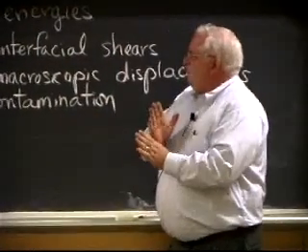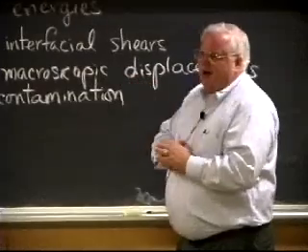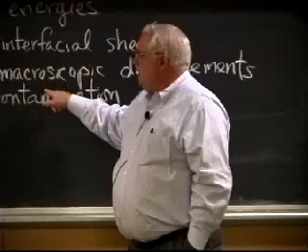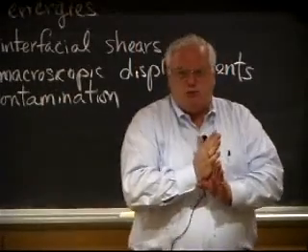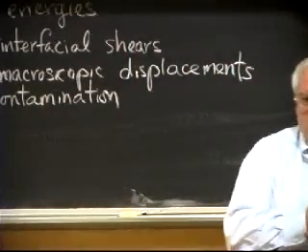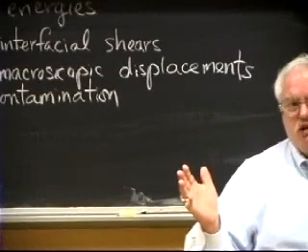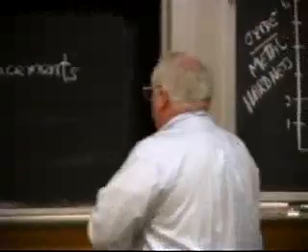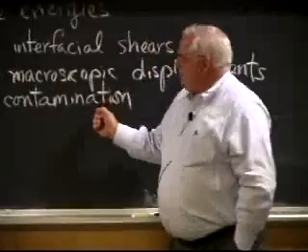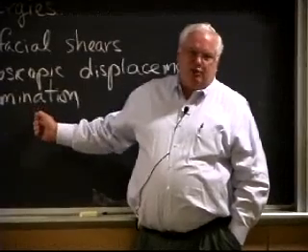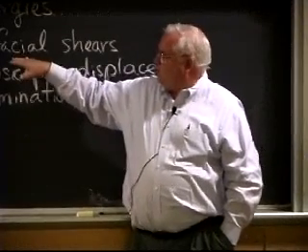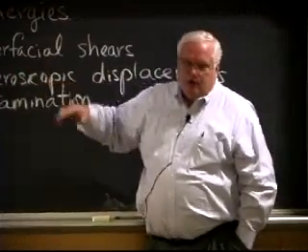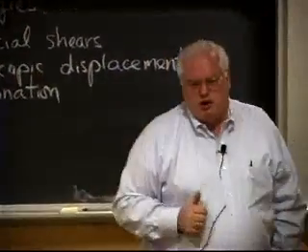Ultrasonic welding is a form of friction welding where you have very, very small macroscopic displacements. The difference is you have huge displacements in friction welding. Ultrasonic welding is essentially the same process, but with very low amplitude oscillations, so your macroscopic displacement is near zero. You can't see anything with your eyes in general. The problem is it doesn't get rid of the contamination, it just displaces it, and so you get about a 50% bonded area in most cases, except that special case I told you about at Sandia. Friction welding, on the other hand, basically extrudes the contamination out of the joint.